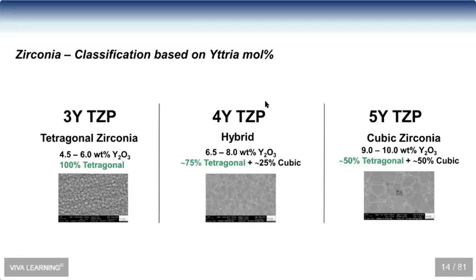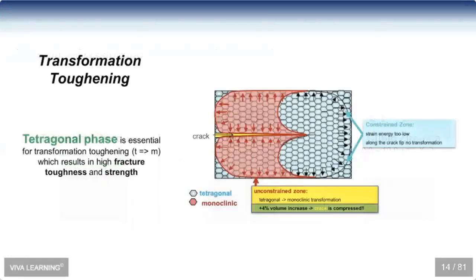The 4Ys were the next step, where it was 75% tetragonal and then 25% cubic zirconia. It's the same cubic zirconia in like a fake wedding ring. And then the 5Ys was the next generation. These are 50% tetragonal and 50% cubic. So these are getting more translucent as we move from left to right, but at the same time, since the less tetragonal phase that we have in here, the less of an ability for the material to undergo this transformational toughening. And that's why it's genius that Emax Prime has the 3Y material at the margin, so you can prep a feather edge or a near feather edge margin and have that strength there. And then at the occlusal or the incisal portion, have the 5Y, where we don't need the strength because the crown is thicker, but now we're going to have the translucency for a more natural effect.